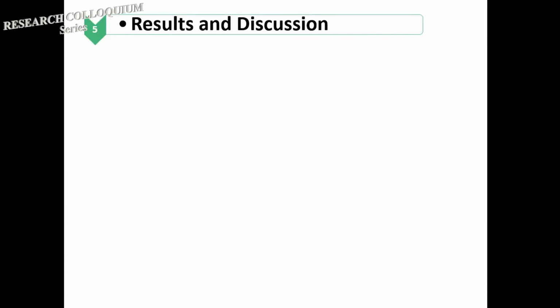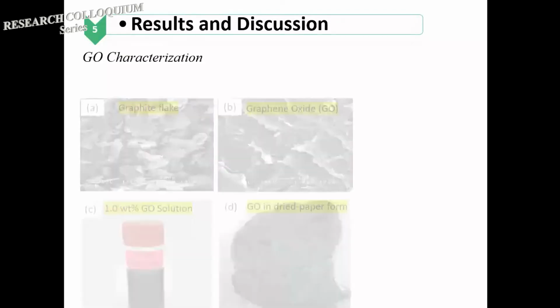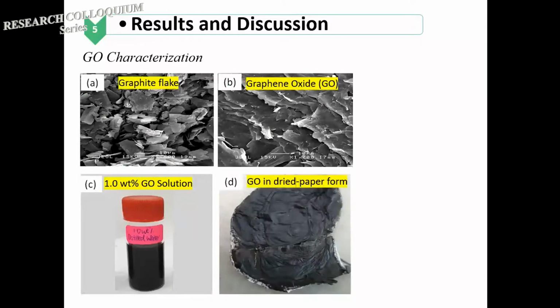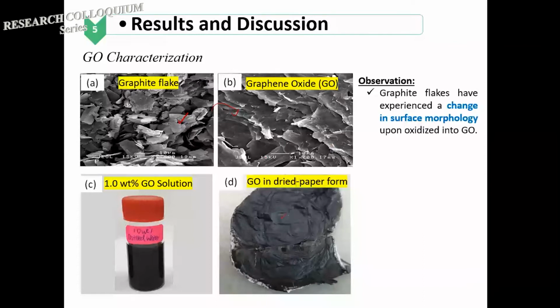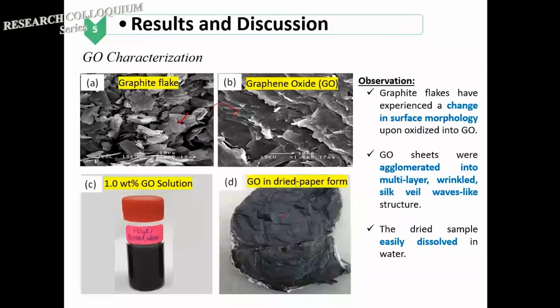As I mentioned just now, I'm working on 5 different types of fluid. The first fluid is distilled water. I go to the characterization first. This is the graphite flake initially, and we successfully made it into graphene oxide. So you can see it's one layer. And this is the graphene oxide in solution form and in dry form. Based on the observation, we found a change in the surface morphology upon oxidizing the graphite flake into graphene oxide. So far it's still good, because the dry graphene oxide can be easily dissolved in any kind of solvent, especially water.